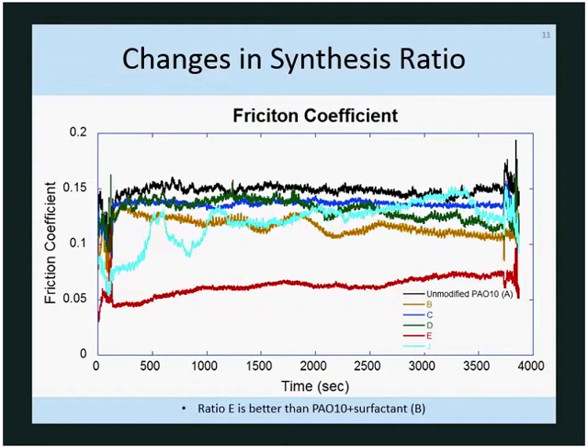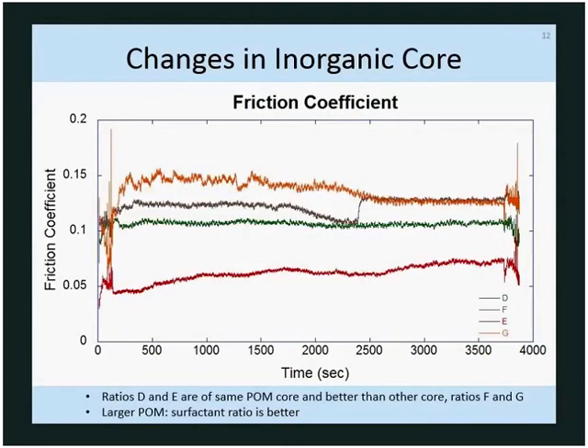And then it's not just, this was using one particular inorganic core. And then it's not just the surfactant doing all the work that is seen, because this yellow one is just the synthetic oil plus the surfactant. So the polyoxometalate is also doing work within that. And then also changing the inorganic core from phosphotungstic acid to silicotungstic acid.